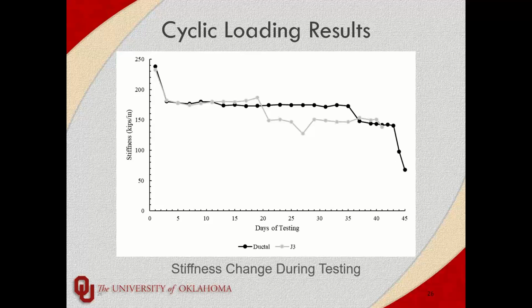But around day 20, we had an error in our MTS pump that operates the ram. And unfortunately, that error caused the ram to immediately apply, I believe it's a 16 kip load, which was about twice as much as what the cyclic load was supposed to be. And because of that, it initiated additional cracks. And that's why that dip in the J3 stiffness plot, that's what caused that, was just that error prematurely cracked the J3 slab, which lowered the stiffness. But at around day 35, 36 is where the 3 million cycles at just below cracking load occurred.